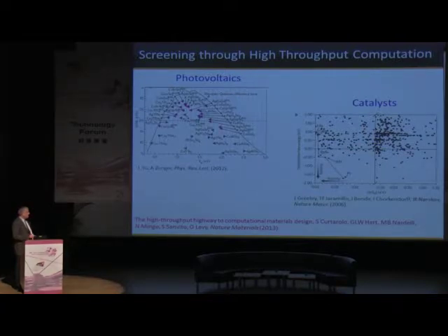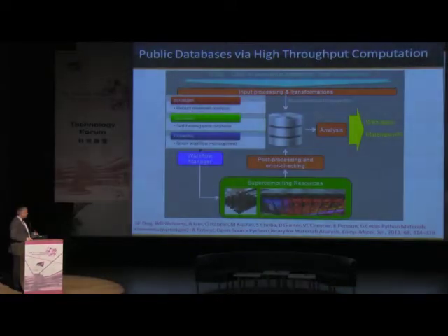They find that basically what you want is materials over here in this corner. The lower the hydrogen binding enthalpy, the higher the activity. And here's platinum, which is a well-known good catalyst, but they actually predict a higher performer in bismuth platinum, by doing this purely computationally on the computer. They actually went ahead and made that and did find that it had a higher activity than platinum. So these are examples where we're using computation in a mode where we're screening over many, many different chemistries and trying to find the best material. These are two examples from the literature.